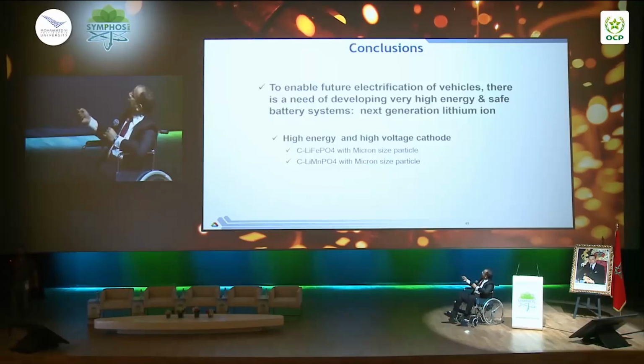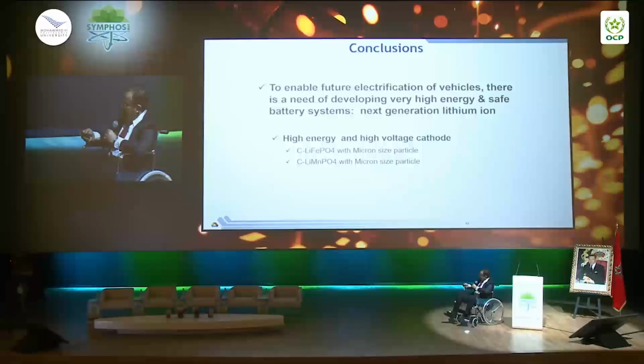My conclusion to you is really, if we want to enable future electrification, we need to develop safe and high energy systems. And I've shown you at least what the community here is interested in. There are opportunities of using phosphoric acid to make very promising, high energy material through the design of the structure where we have micro-sized particles that have nanopores, where you can impregnate the electrolyte in the pores and increase the energy without compromising the power. I've shown an example of the iron phosphate, and also the manganese phosphate is very attractive as well.